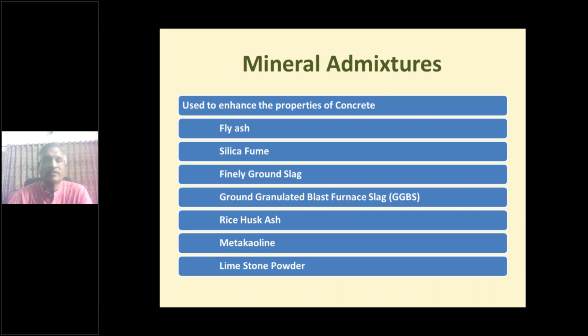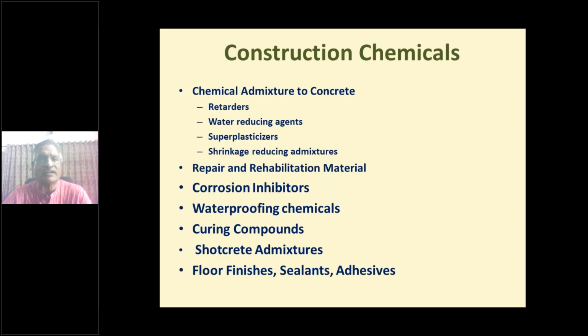are quite different. Other mineral admixtures that we use as replacement of cement are fly ash, silica fume, finely ground slag, GGBS, ground granulated blast furnace slag, rice husk, metakaolin, and limestone powder. Whole lot of materials are coming. Then we have also come to use a whole lot of construction chemicals. This is one of the most exciting fields. That is, properly we are cooking concrete. You give the parameters that you want, and they can be produced by using proper construction chemicals.